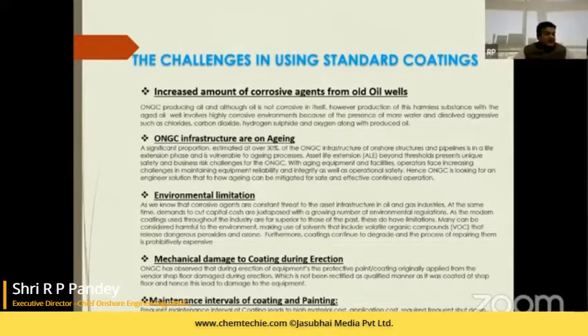Environmental limitations are there, as is mechanical damage to the coating during erection. Once we take material or equipment coated from the plant, during transportation so much damage takes place, and coating at the site which is not compatible with the original coating is also a challenge. Then there is the maintenance interval of the coating system. Some coatings we have to redo every year, somewhere every 2 years. The coating intervals are still very short because of environmental conditions.